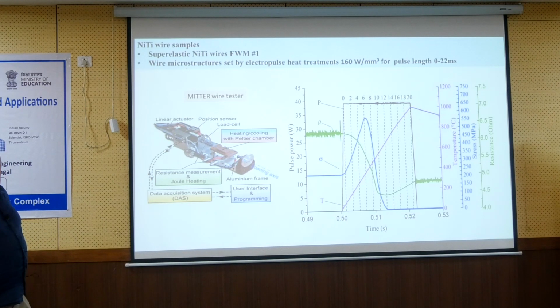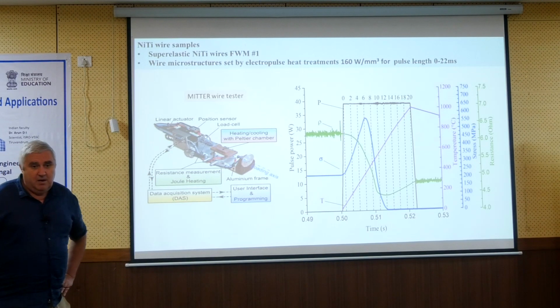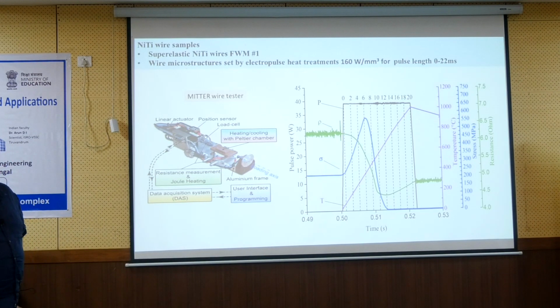So basically, this is a test to show that austenite is there in the wire, right? Sorry? It's a way to characterize austenite by the resistance. Well, this is the way to heat treat the metal. Okay. Yeah, I am just showing the details of the method.